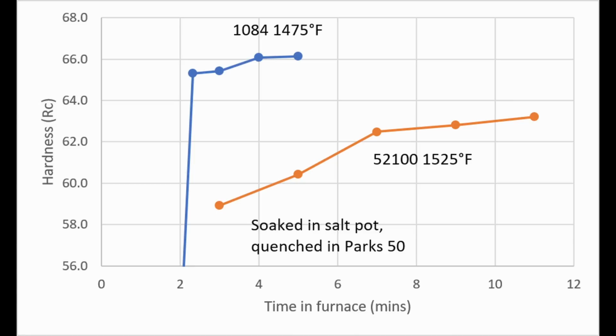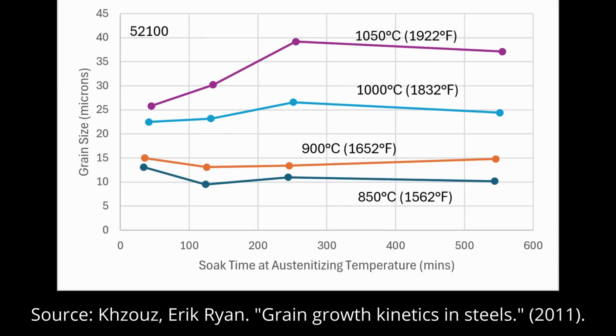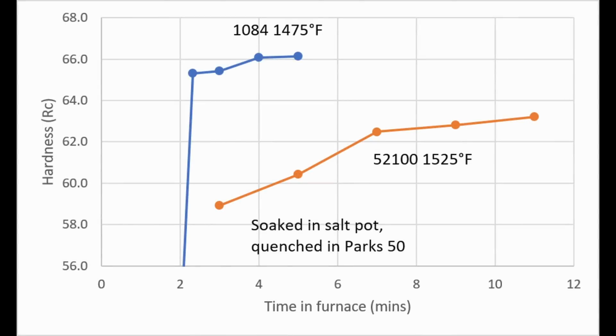If you're using the right temperature, you don't need to worry too much about grain growth. Even holding for an hour, the grain size isn't going to be significantly larger than a 10 or 20 minute hold. Temperature is more important than time. So it's important that you soak long enough where you are getting into a consistent range of hardness, even with different size pieces. Now, of course, you can soak a little longer if you have larger pieces as well, but ensure that you've soaked long enough. That is more important than trying to shorten your soak time to try to get finer grain size.